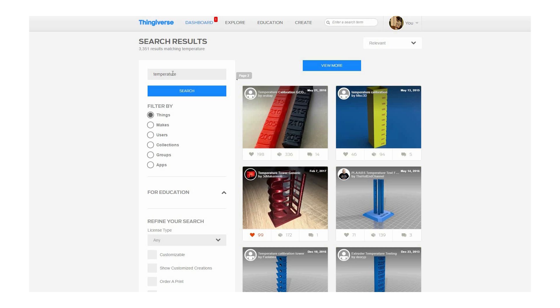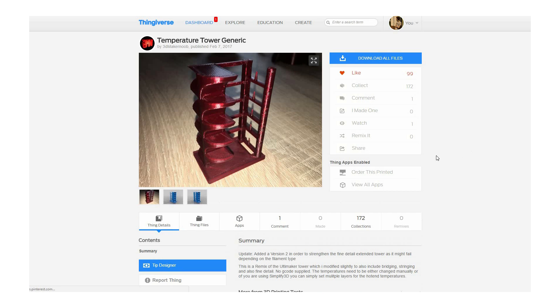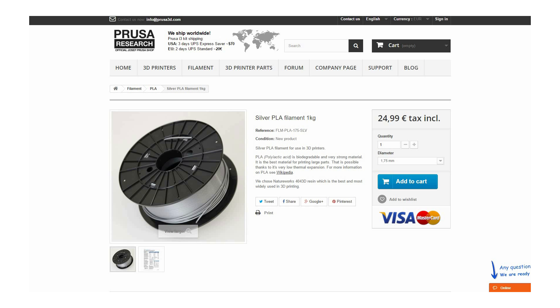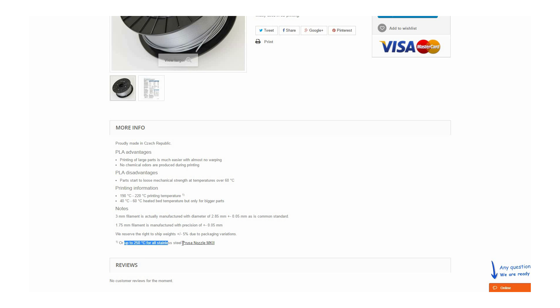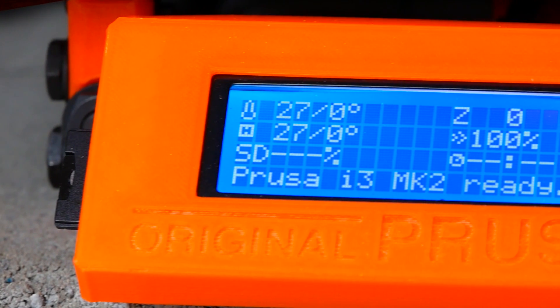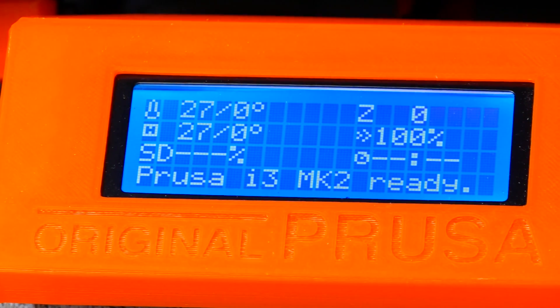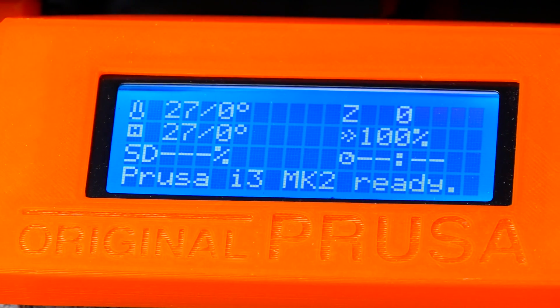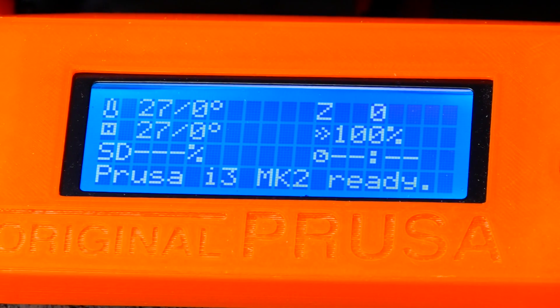At first I needed to define the temperature range. Since you won't be able to use 3D printing temperatures that result in good properties but produce horrible print results, I printed some temperature test towers which can be found on Thingiverse. Prusa recommends temperatures from 190 degrees to 220 degrees for their PLA. Since my test part was designed for 5 different temperatures, I went from 230 degrees Celsius to 190 degrees in 10 degree decrements. Keep in mind that these temperatures are specific for my printer and my Prusa i3 Mark II, at least at ambient temperature, shows slightly elevated values.